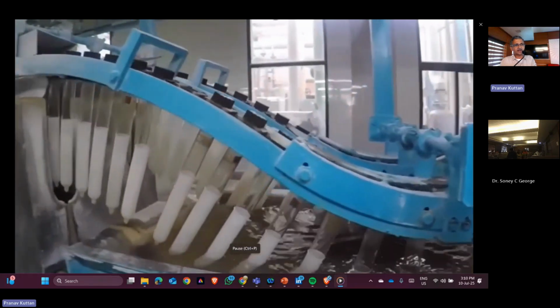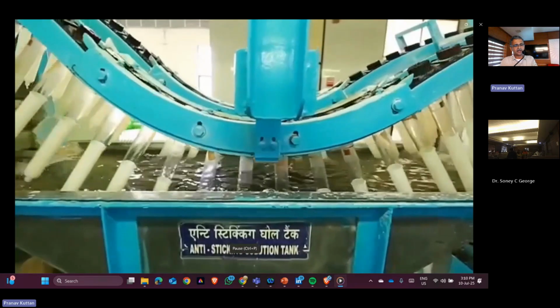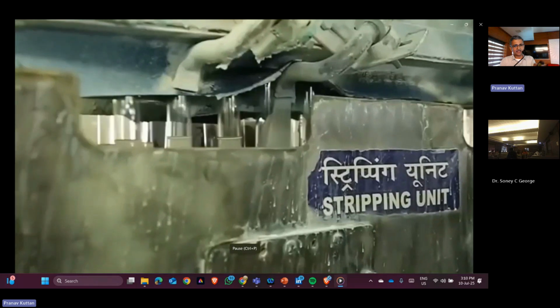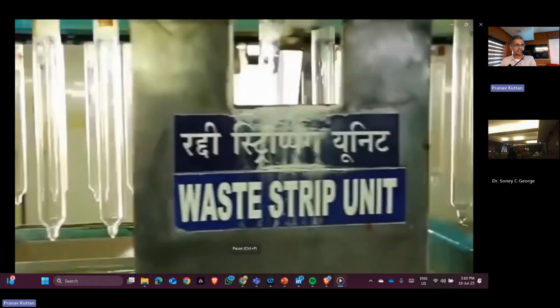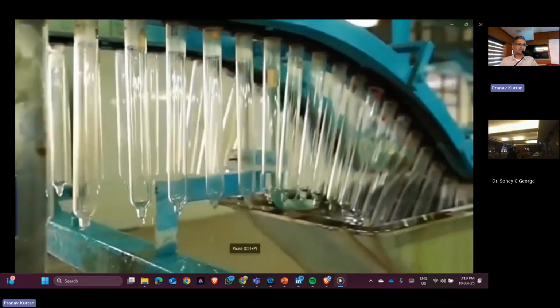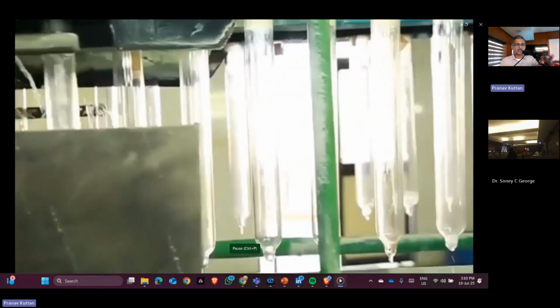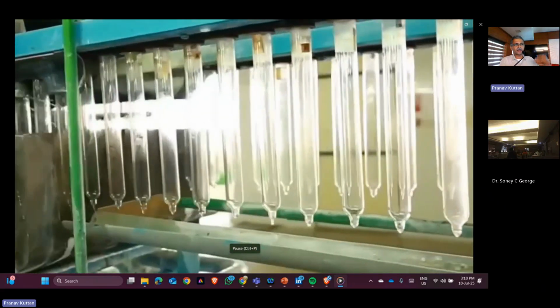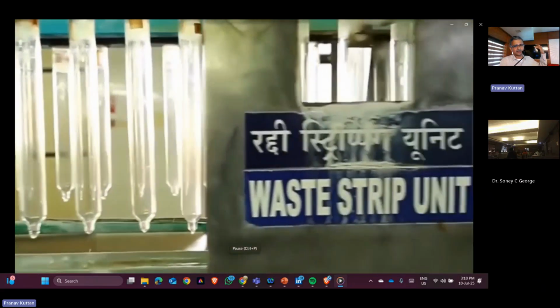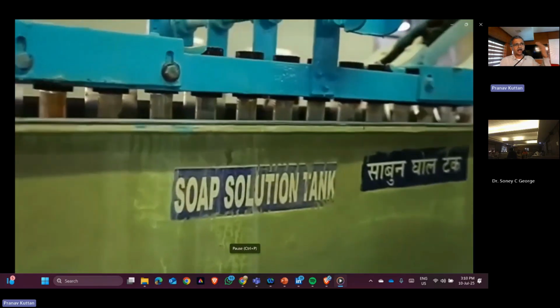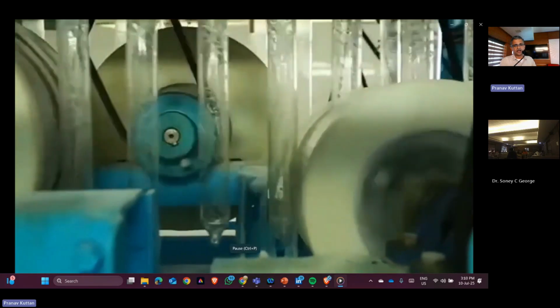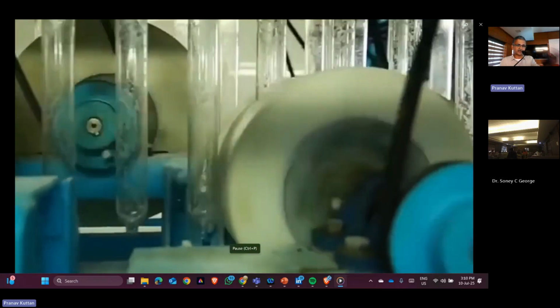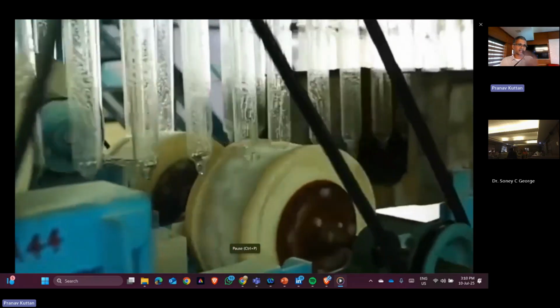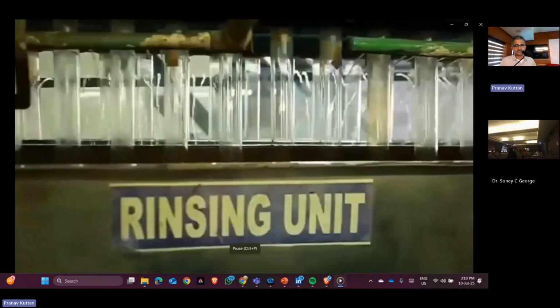Once the dipping is over, it is formed into the mold as a thin film, and then it is passed through the anti-sticking solution, and it is stripped using a silica slurry, where it is taken to another place where it is kept in the oven at a high temperature of around 80 degrees Celsius for a period of 1 hour or 45 minutes. And the molds are getting cleaned, washed, and then going for re-dipping in the dipping lines.